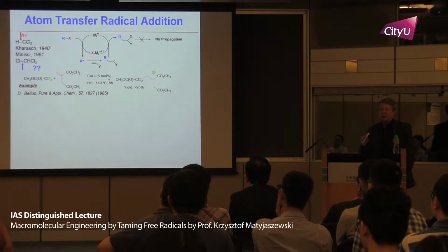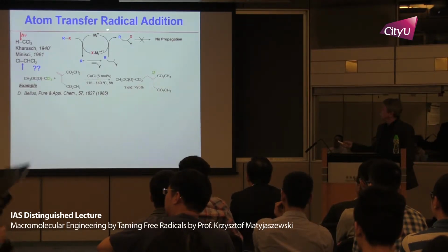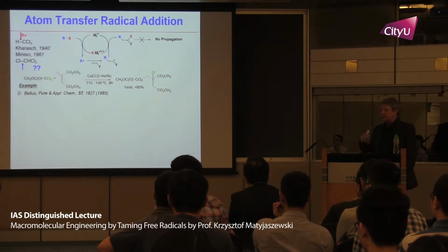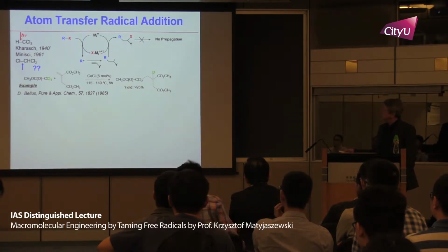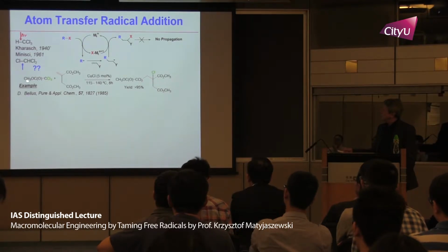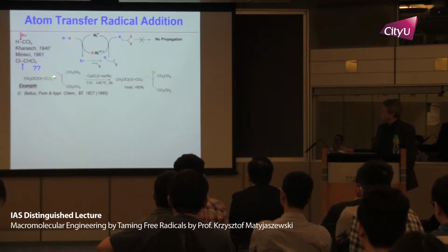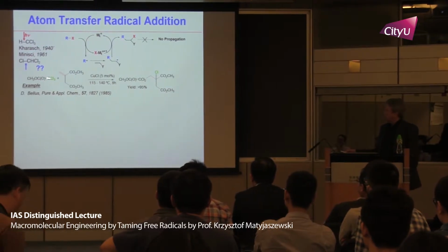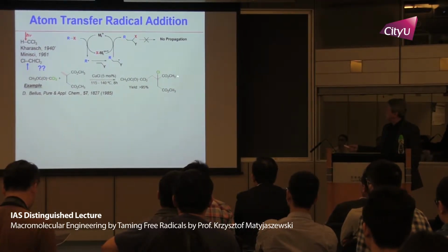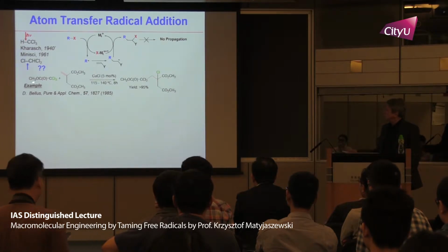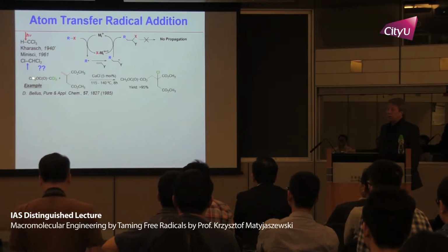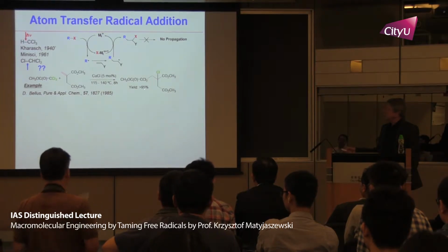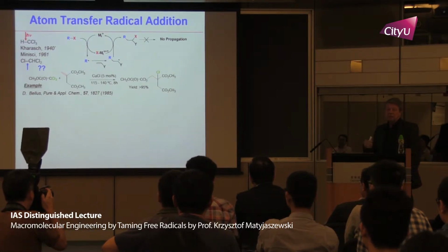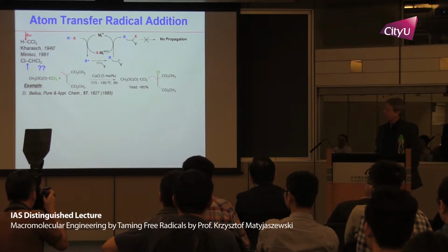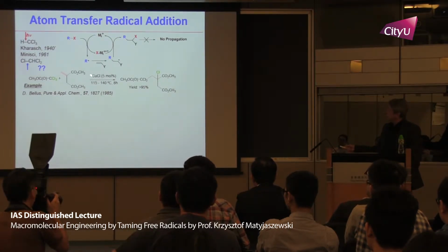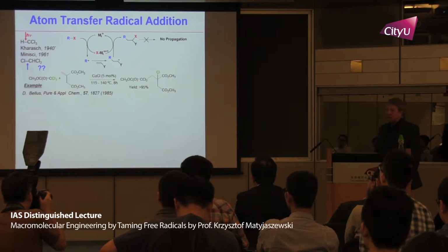So a trick for organic chemists was to make only this adduct, one-to-one adduct. So they selected structure of compounds in such a way that substrate was much more reactive than product. So you could see here 3 chlorine atoms, carbomethoxy group. After addition, 1 chlorine atom and 1 carbomethoxy group. So this is approximately 100 times more active, which means that isolated yield of a product was 95% and spectroscopic 99%. You could see here that the amount of a catalyst was around 5 mol%, a lot.